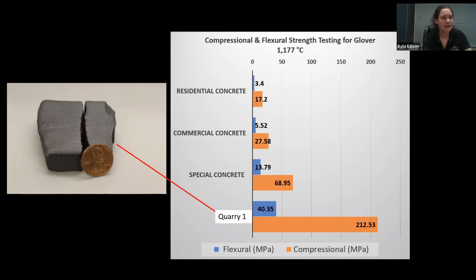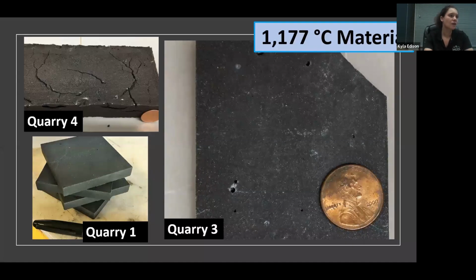And so we had this really strong material compressionally that just blew special concrete out of the water, but it just kept cracking. And so we needed to figure out why and how to stop that, and if it was possible to stop it. And so again, using different materials from different quarries and changing the sintering process a little bit, we figured out how to come out with this material that wasn't cracking. And so you can see Quarry 1 and Quarry 3, they're very similar looking.